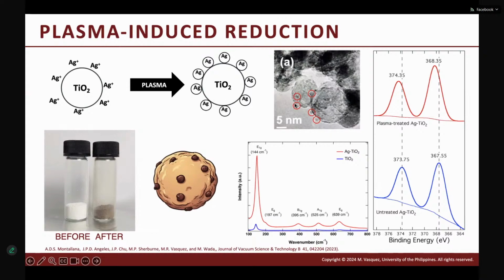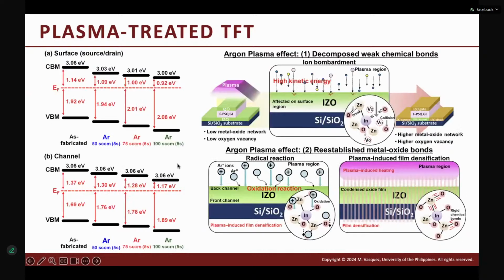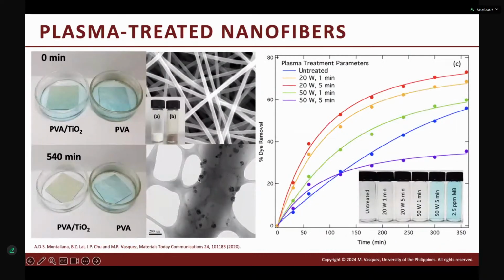If you can see here in the TEM, we have small particles of silver. We also use Raman to verify the presence of Ag, because Ag, if it's in a nanoparticle, has plasmonic properties, so it actually enhances the signals of TiO2. Once we have these Ag TiO2 nanoparticles, we embed them in the nanofibers, and we expose this to plasma so that some of the particles will be exposed on the fibers, and then we use visible light to degrade a test analyte like methylene blue.